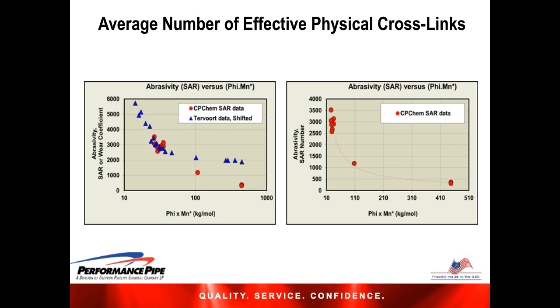And then that Chevron Phillips data is shown on the right just by itself, and you can see the very same trends that we saw earlier, which is that the slurry abrasion response number is an exponentially dependent factor in terms of these physical crosslinks. So this basically validates our thinking and further validates the fact that the medium density pipe with the higher number of physical crosslinks should have, as the data then supported, significantly improved abrasion resistance.